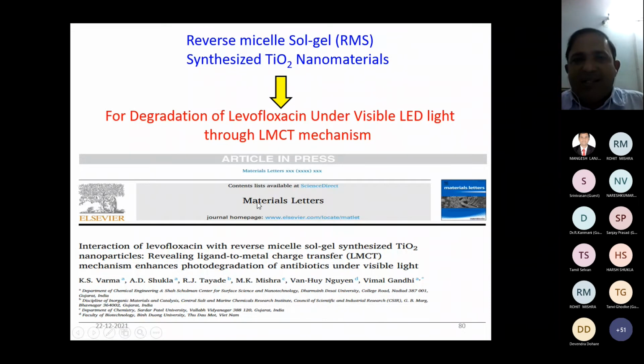Okay, so our another article that is in press was selected in Materials Letters last month in November, and here we are reporting a different mechanism. Up to this point, we discussed that TiO2 is not working under visible light because of its energy band gap of 3.2 eV. But surprisingly, we found that the synthesized TiO2 works under visible light for this particular molecule levofloxacin, and levofloxacin promotes one mechanism known as LMCT, ligand to metal charge transfer, and this levofloxacin molecule itself works as a dopant and enhances the performance of TiO2 under visible light.